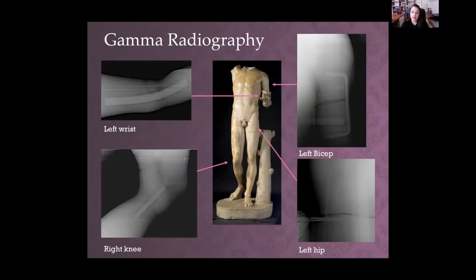Both, like Andy was saying, the knee that you see on the lower left-hand side was extremely delicate. And I was very concerned that any movement or stress put onto the sculpture itself would cause damage to this knee, and we did not want that to happen. When we did the gamma ray, we had to do it down in the boiler room of the museum because they brought in a radioactive source. We had to make sure that no one was around, and it was on a day that we were closed, on a Monday. And so we were able to really identify what was going on inside of the sculpture, as you see here.